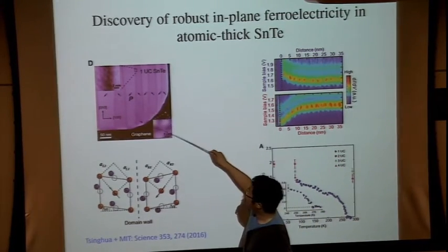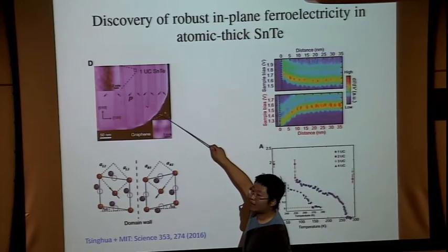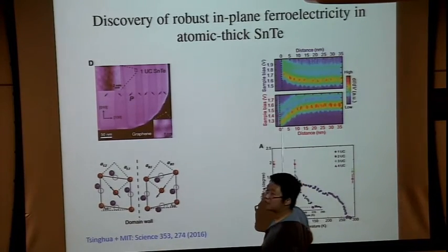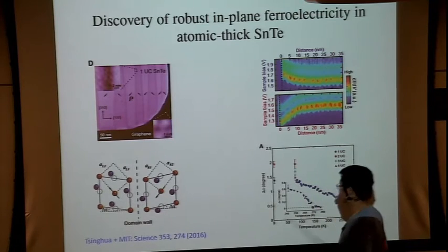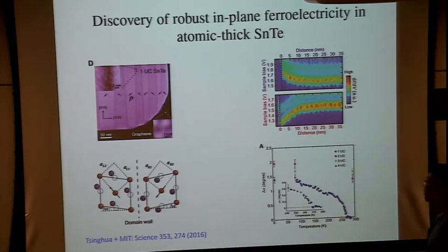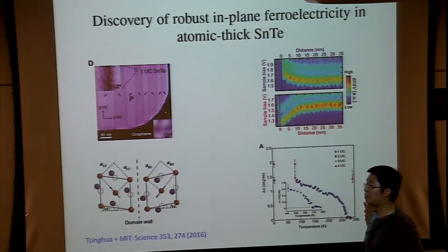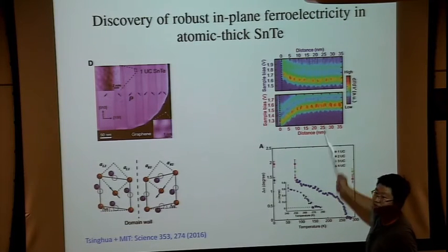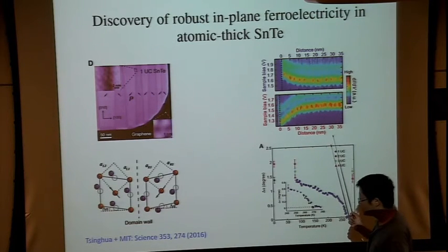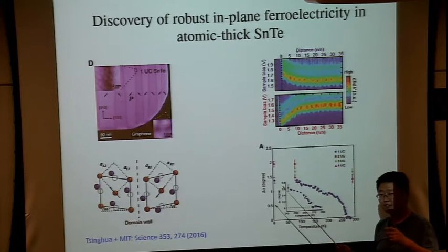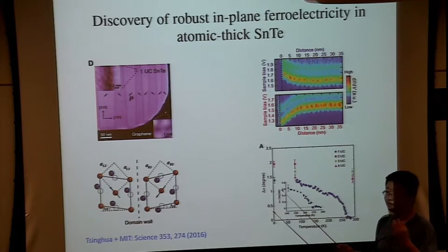And for a given domain, if you move to the left and to the right edges, the band bending goes in opposite directions. So this is evidence for the structural distortion generating a ferroelectric polarization. This is also confirmed by the quasi-particle interference, which shows that the lattice Bragg peaks actually split and distort.